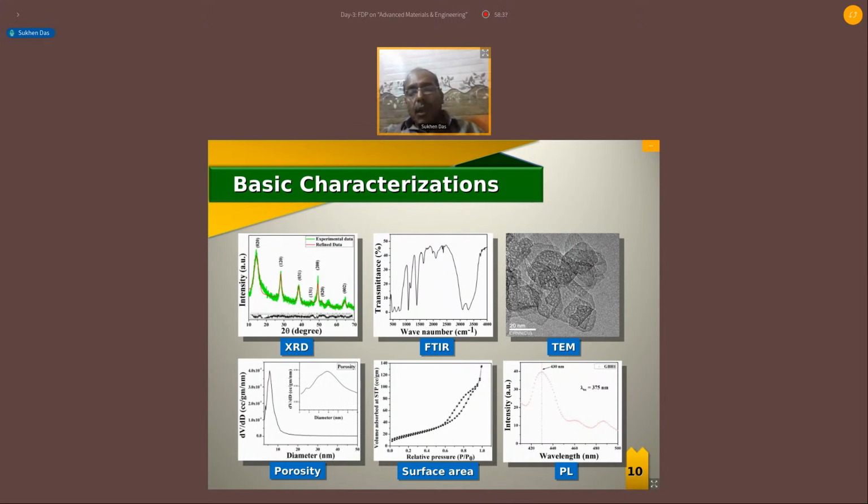From the TEM study, here you can see, it is clear what we have decided. The picture is also saying the same thing. That means the crystal size of the boehmite particle is in the order of 20 to 30 nanometers, and the dotted form upon each crystal is nothing but the indication of the presence of the resin, that means the gum acacia on the surface of this. And this gum acacia is making this boehmite more soluble in water.